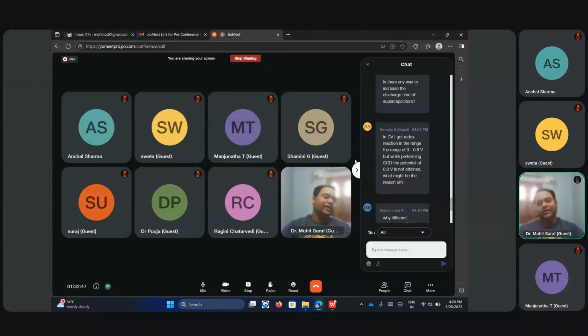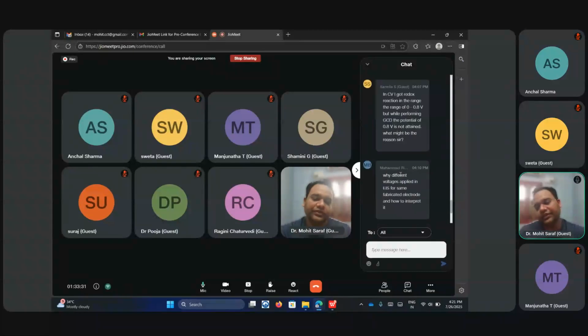If you have optimized your electrochemical window in CV to be 0 to 0.8 volts, then in GCD you will surely get 0 to 0.8 volts. It's possible your optimization in the CV itself was not correct. But if it's not coming in GCD, I think there is some problem. Ideally you should always present the same electrochemical window in CV as well as in charge-discharge, so there's no point explaining further - you should just redo the optimization, re-optimize your system. Your potential window should be equal in both CV and GCD.